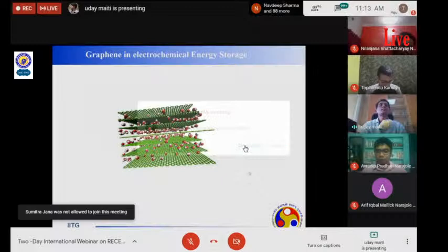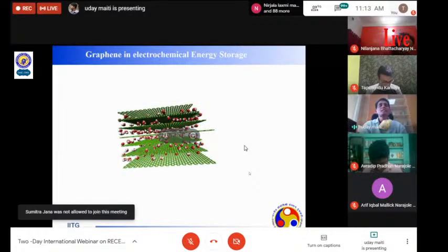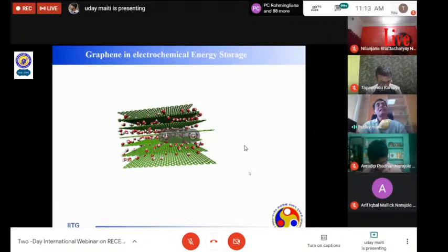But there is a real issue. The issue is that because the graphenes are two-dimensional sheets, they have strong interaction to restack back in terms of the graphite. People can make the graphene from the graphite, but the graphene again has a tendency to restack to go to the graphite phase. And if they restack, then you cannot access the intermediate layers. You can just access the outer layers only. So how to restrict this restacking problem, which is a huge problem for graphene-based systems in energy storage?